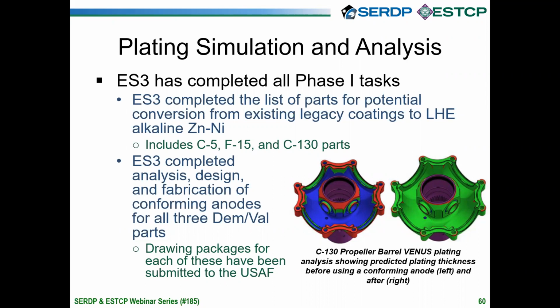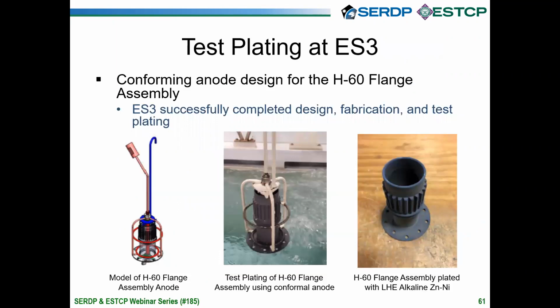You can go to the next slide, slide 61, Greg. This just shows the test plating. The next 3 slides are going to show the test plating of the part. So you can see on the left, you sort of start at the design phase. Your pink would be things that are covered in masking, stainless steel that holds the anodic portion, the dark red, and you can see dark red in the middle there, which is the nickel 200, and the blue would be on the cathodic side. Before we plastisol these, which we see everything masked, we'll do a test plate, make sure everything plates properly within spec, 0.5 to 0.8 for class 1, 0.3 to 0.6 for class 2